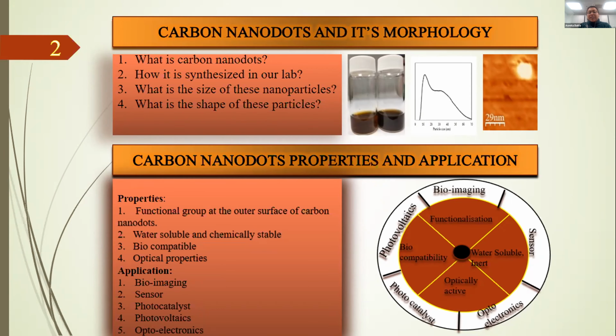How is it synthesized in our lab? In our lab, it is synthesized by bottom-up hydrothermal treatment of urea and citric acid solution. We take urea and citric acid solution in water and put it in a microwave for 10 minutes. It is washed and cleaned after that for further use.